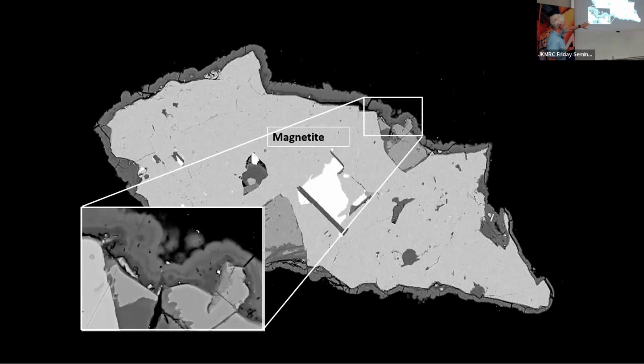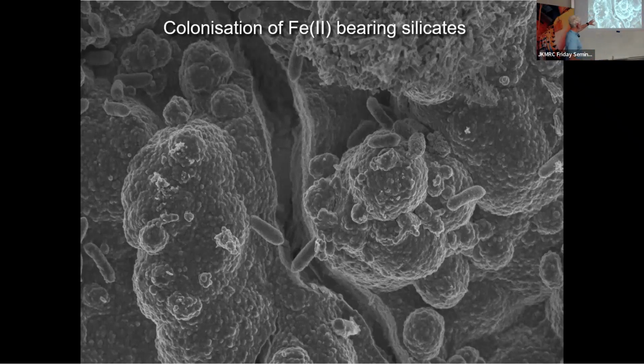In terms of the magnetite, we produced a complete corrosion crust around the edge. And in this higher magnification, you can see the bacteria that have been permineralized and trapped within that oxide boundary. For the silicates, it's iron 2 silicate. It's loaded with bacteria that are growing all through this system that are promoting weathering and potentially passivation of these mineral grains by the secondary mineral formation in this system. And so with all these examples, bacteria are extremely well adapted to getting electrons from wherever they can.